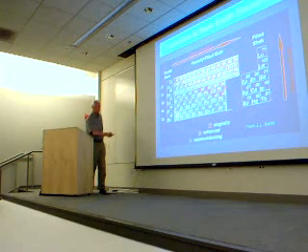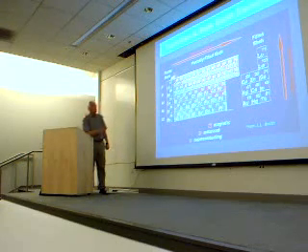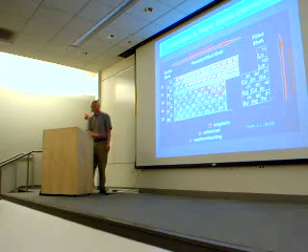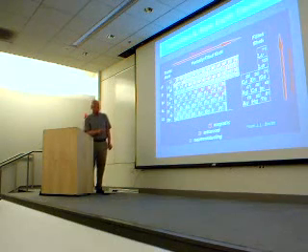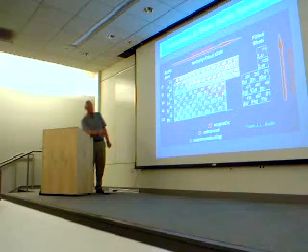If you look at the 3D elements, then if you go down to the 4D and 5Ds, they are rather band-like and not very localized. And there's an interesting stripe across here that's meant to be a different color. That's where all the anomalous systems lie. Exaggerated, excuse me. If you just look along that line, you'll find everything has an anomaly. Cerium has this change in volume at a little bit of high pressure. It happens in neptunium and plutonium. Plutonium is really complicated.